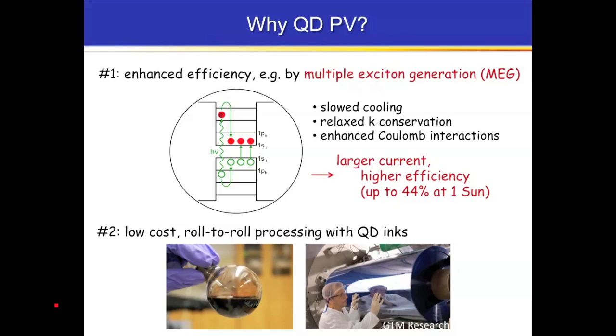So for example, multiple exciton generation is the process whereby you can absorb a high energy photon, and instead of just creating a single electron hole pair at the band edge, you can make two or you could make three, for example. And if you can do this process efficiently and extract out the multiple carriers, then you can, in principle, get to a device efficiency as high as 44% at 1 sun compared to the Shockley-Queisser limit of 33. So this is one motivation. You can also imagine using quantum dots for hot carrier effects as well as cheap multi-junction devices.